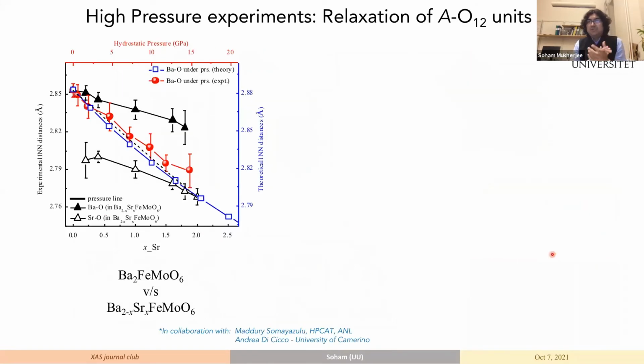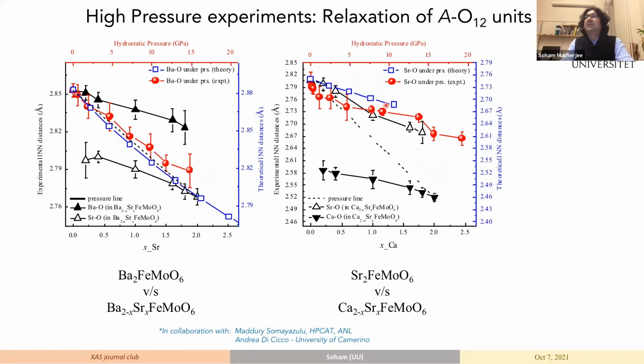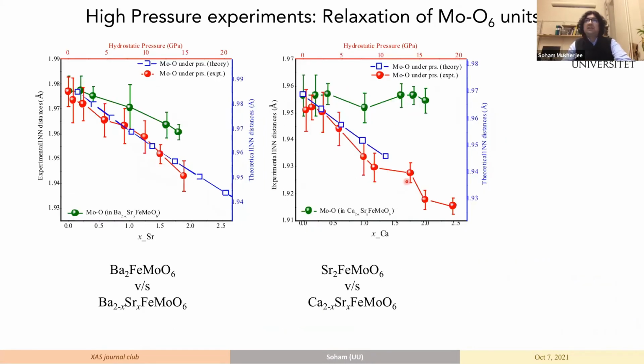And this was done in collaboration with Madhuri Somayazulu and Andrea Di Cicco at two different experiments were performed. And you can see when you do high pressure experiments on barium, iron molybdenum oxide, and you do chemical pressure by substituting strontium, the high pressure data set shows that it scales very well with the chemical pressure line. Whereas when you look at the data on the strontium doping with calcium, which is the positive chemical pressure effect, we see that the physical pressure line does not follow the chemical pressure line at all. This is also reflected in the molybdenum oxygen data.